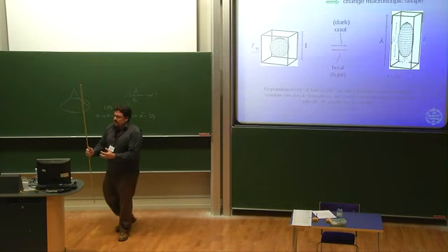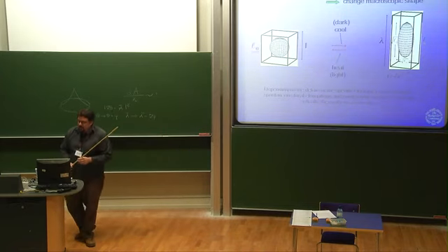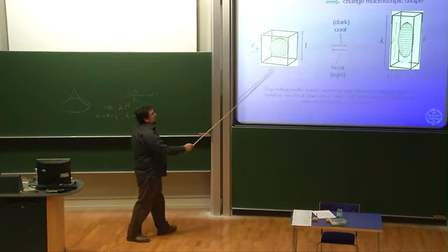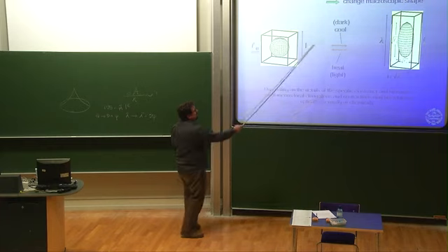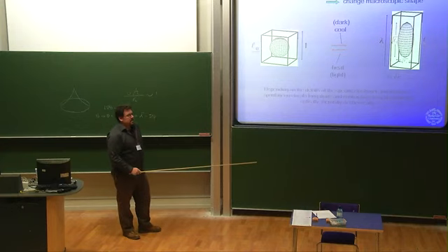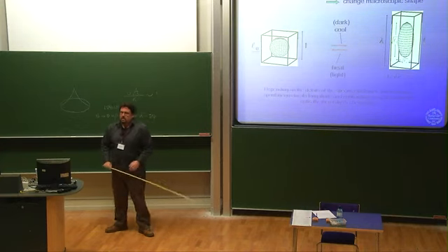This is the basic microscopic idea. You can activate it any way that you can change the order parameter, through temperature or chemicals or even light, depending on what the mesogens are. You get this order parameter-driven change in shape.